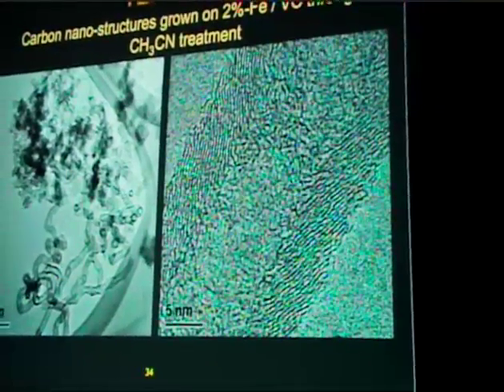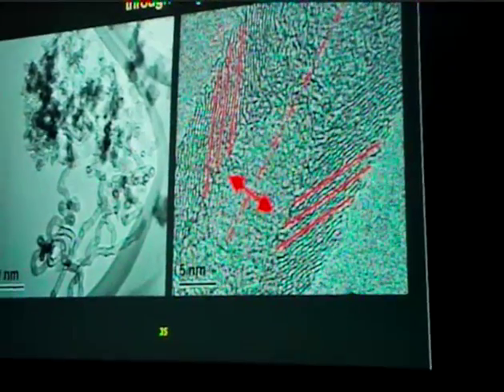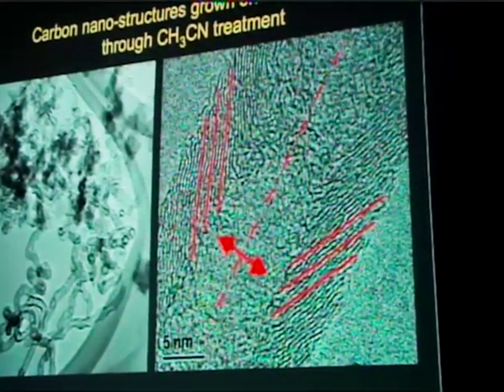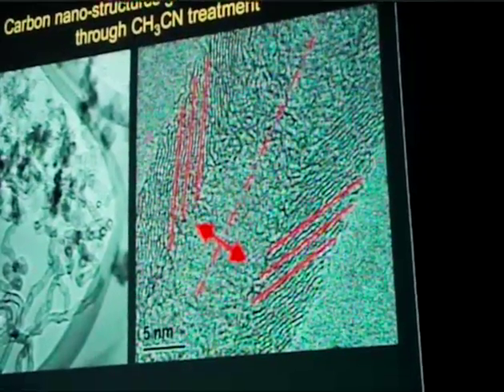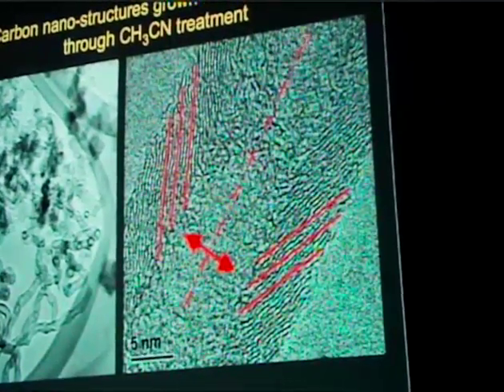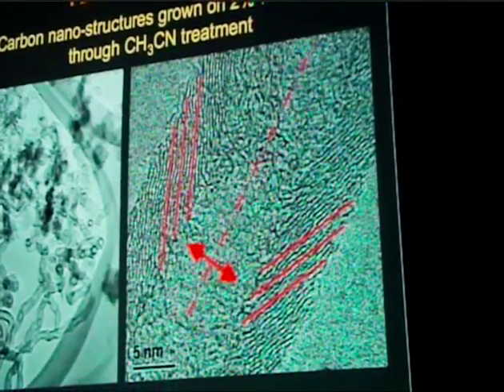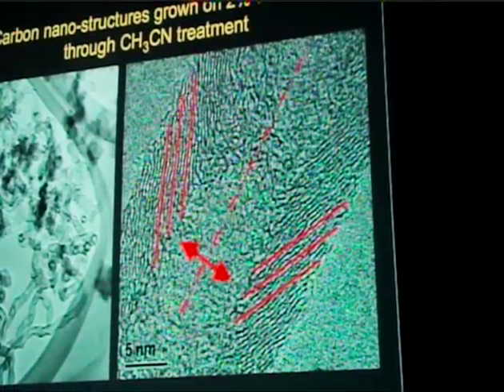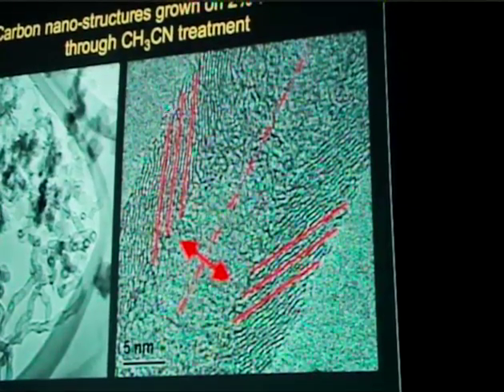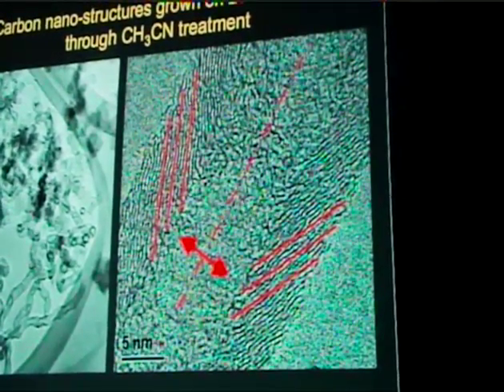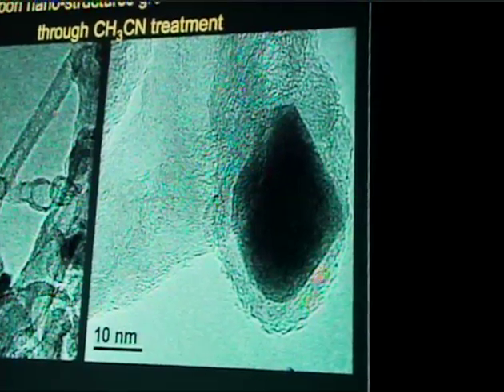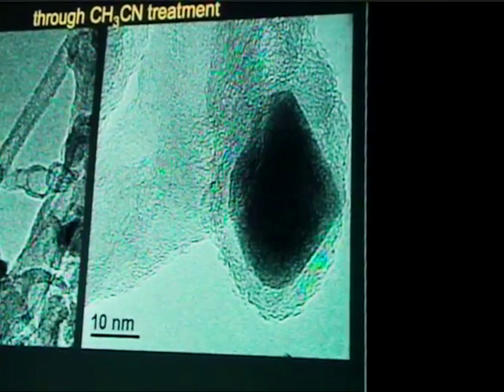And here is a single fiber, and if you look closely, and maybe if I draw the lines, the graphitic planes are at an angle to the axis of the fiber. So as you can see here, the graphite planes are ending at an angle, and all of these are exposed edge planes. And also, if we look at the tip of one of these fibers, you can clearly see the pear-shaped iron particle at the tip of the fiber.